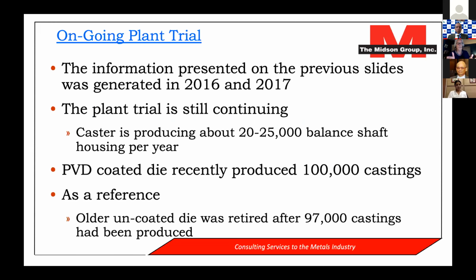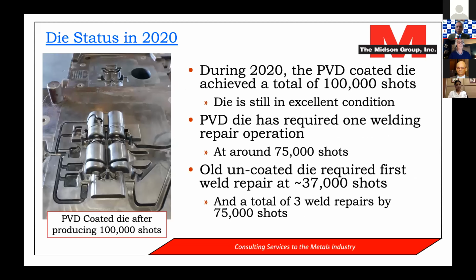And as I said earlier, as a reference, the older uncoated die was retired after 97,000 castings had been produced. So we're already doing better than the old uncoated die. And so here's a photograph of the PVD coated die after more than 100,000 castings have been produced in it. At the bottom, you can see the ejector side, at the top, the fixed side. And certainly looking at this view, it seems to be still in excellent condition, even after the production of 100,000